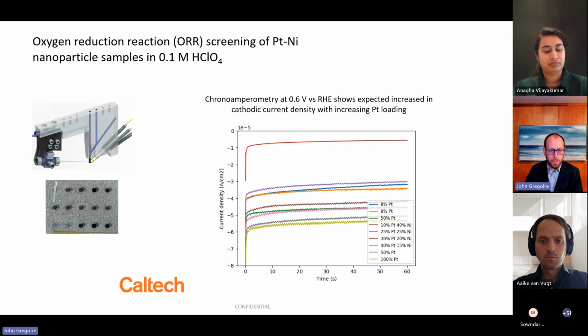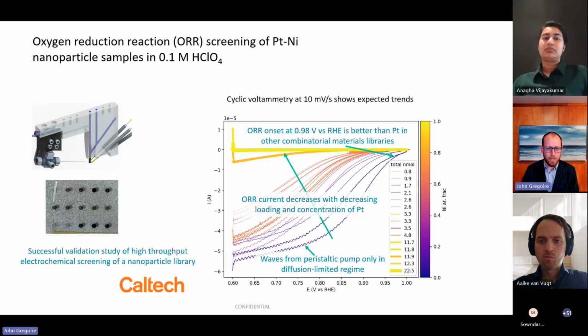And initially, looking at these chronoamperometry measurements, we're seeing the expected trends, which were also mimicked in data I'll talk through a little bit more. This series of cyclic voltammograms, where purple means it's platinum, yellow means it's nickel, and the width of the line corresponds to its metal loading, which we also varied in this library.